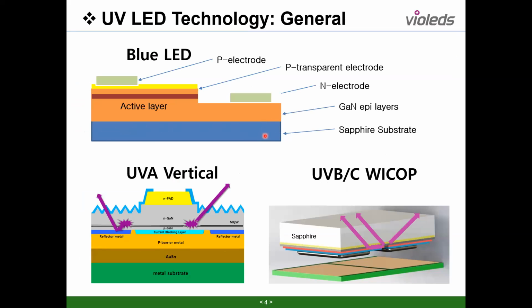But even though we have some technology, there are still some defects. To reduce the defects, we grow high-quality layers. Actually, we only need the active layer, but to support it and to have a high-quality active layer, we grow a several-micrometer gallium nitride layer. Another role of the gallium nitride layer below is to transport electrons to the active layer. So the electrode is here, and then the electrons move to the active layer, to the N layer.